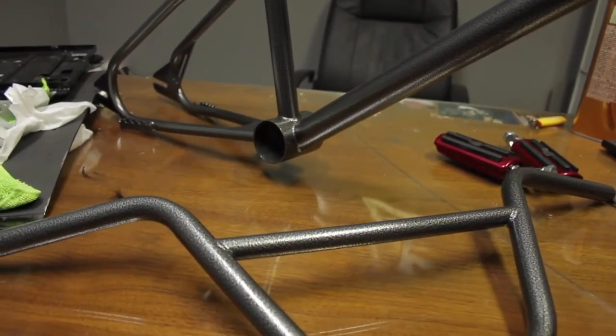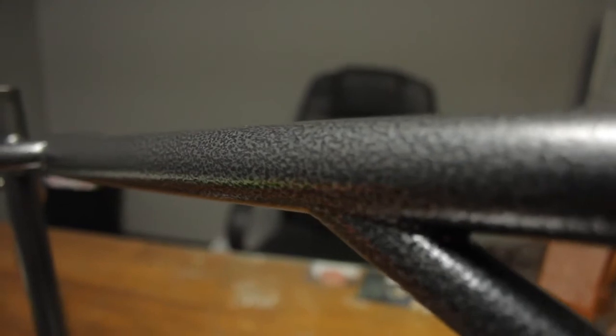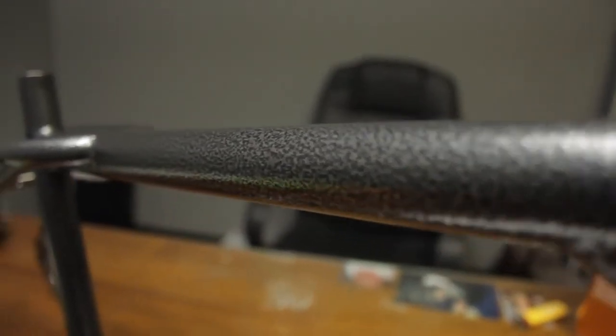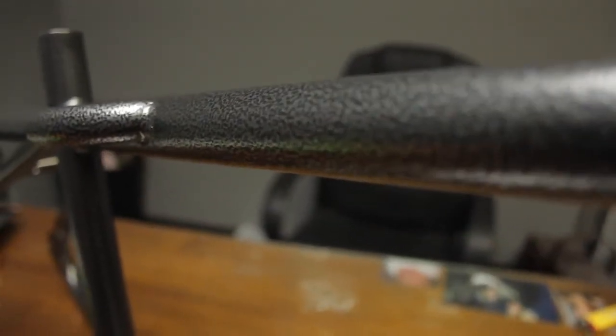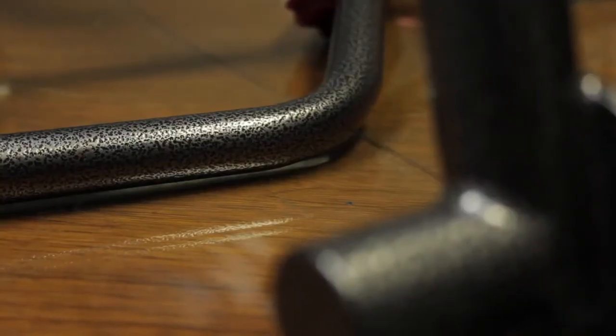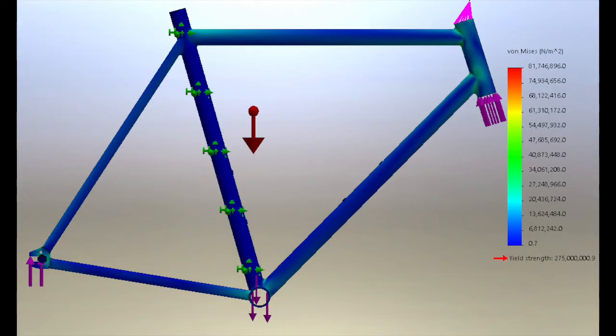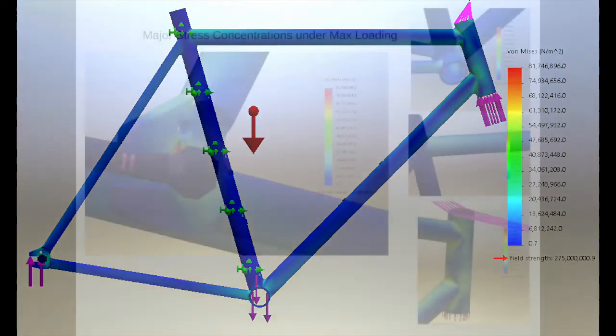Then, the powder is cured at 200 degrees Celsius for 10 minutes for a more uniform finish. This process takes approximately 45 minutes from start to finish. After selecting a material, we chose to simulate the effects of a maximum loading case on the frame. Many assumptions were made when looking at the impact case of the frame, which included a completely rigid suspension and factoring down the maximum loading case to make analysis easier and quicker.